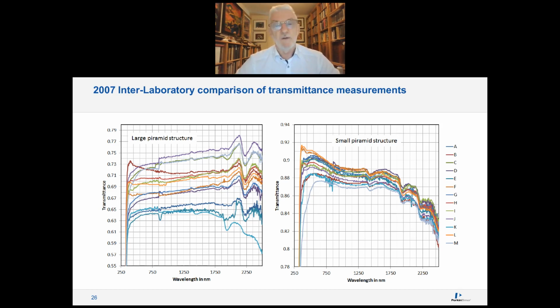But with this type of sample, it was completely off. They proved that with the existing tools they had at the moment, and most of them used small so-called integrating sphere accessories, the standard 150 millimeter accessory was widely used, they could not get good agreement. So we started to investigate what the actual issues are. Of course, that's one of the things we do in my company: we investigate measurement problems, find a solution, and then turn it into basically a spectrophotometry accessory which can do the measurement accurately.